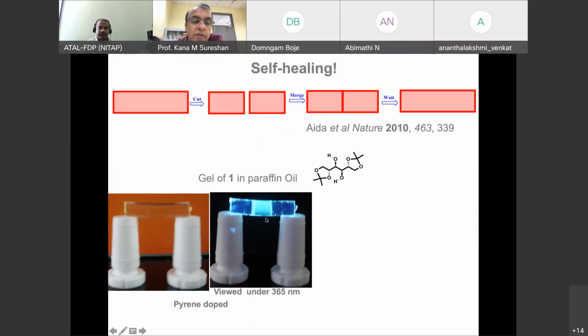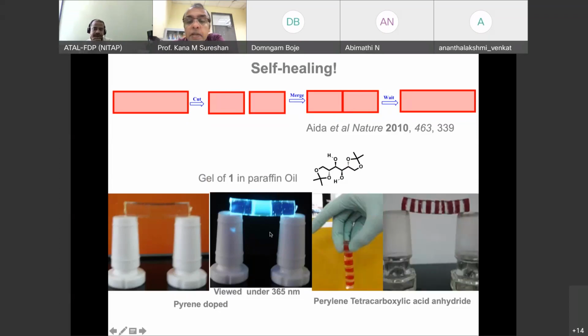To visualize that, we have taken the middle piece and daubed it with pyrene. Pyrene is UV active, as you know, and in the UV light you can see 3 different blocks here. Also, we can make many such pieces together. This is 18 different blocks, small discs we have combined and put together, and after some time it self-healed. In the 18 discs, the alternate ones are daubed with PTCDA, perylene tetracarboxylic dianhydride, which is a colored substance. You can suspend them vertically or horizontally, they are stable, they are self-healed. So now this is good for our application.